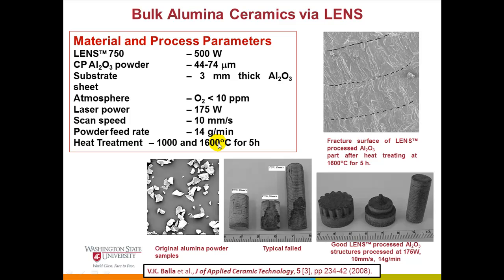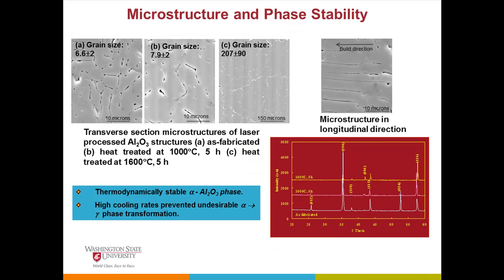If you look at this, the grain size is 6.6 micron as fabricated, and after heat treatment at 1000 degrees it increases a little bit.